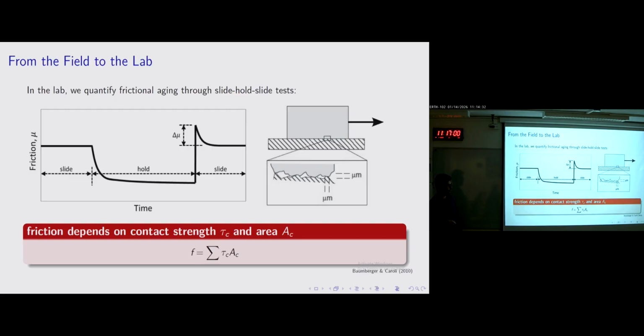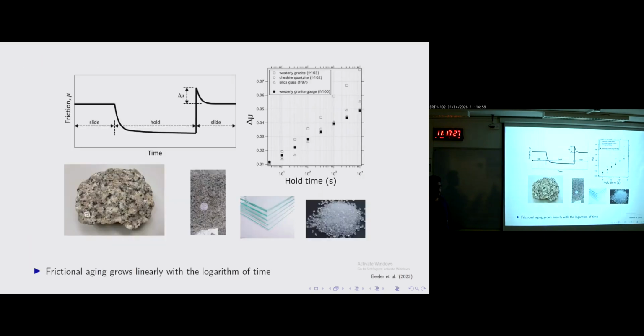And the friction force is actually the summation across all the asperity contacts, and it's dependent on the inherent shear strength of the contact times the contact area. So just keep that in mind. That's friction, and it's controlled by these two parameters. And we'll start looking at what happens from previous experiments and studies on slide-hold-slide tests.